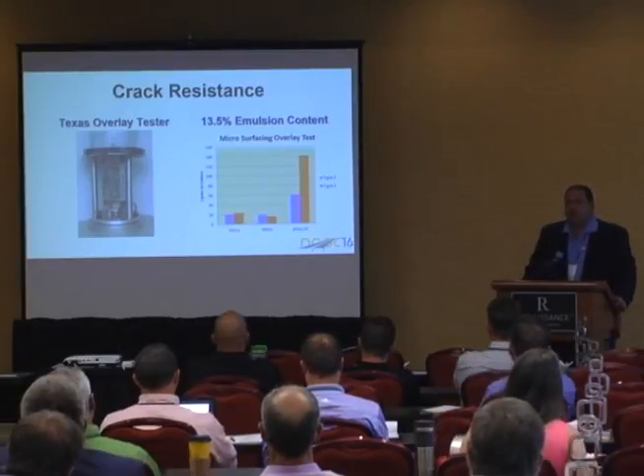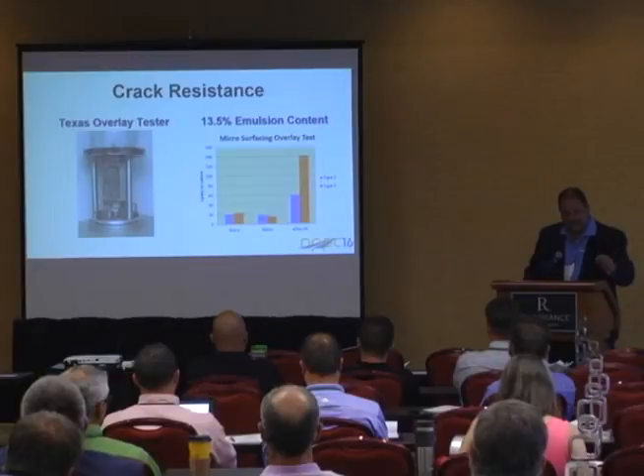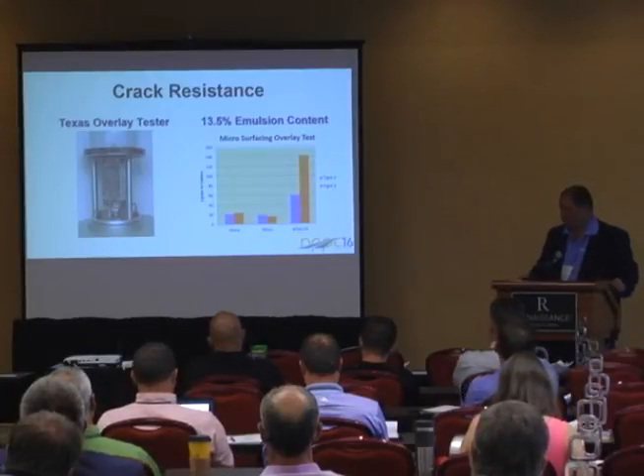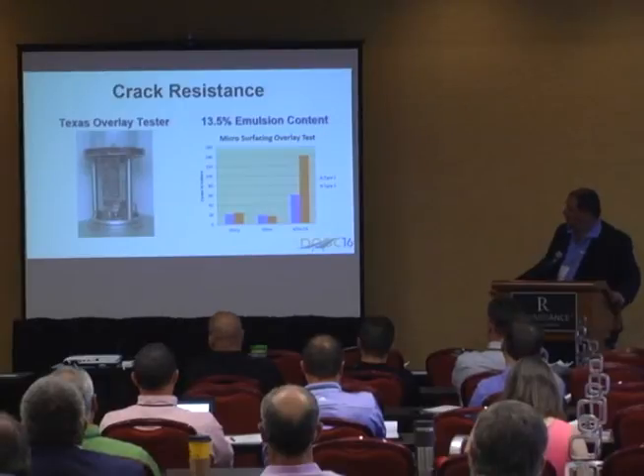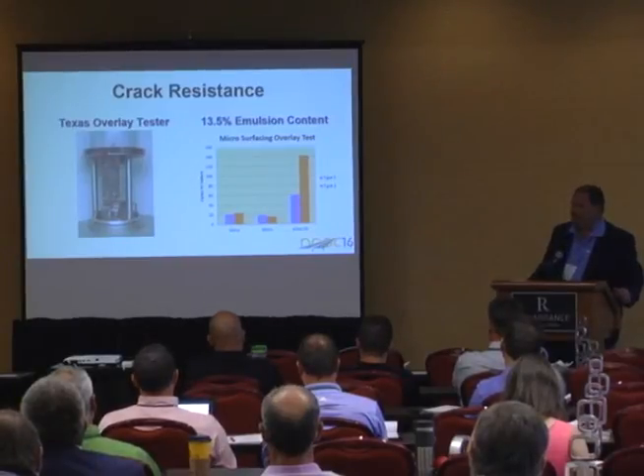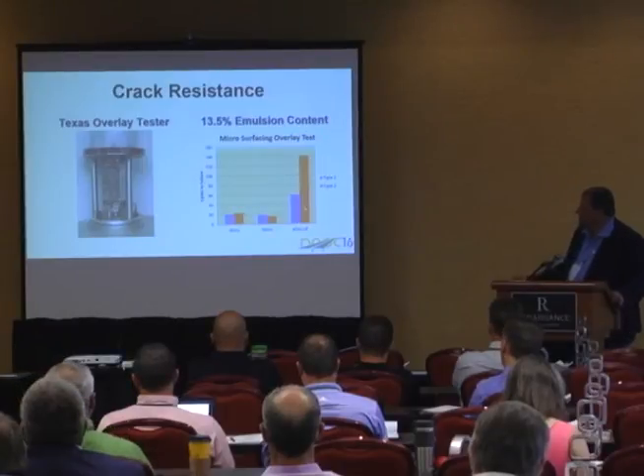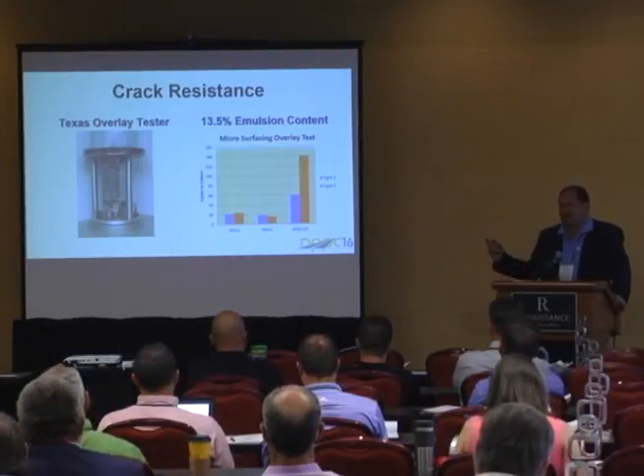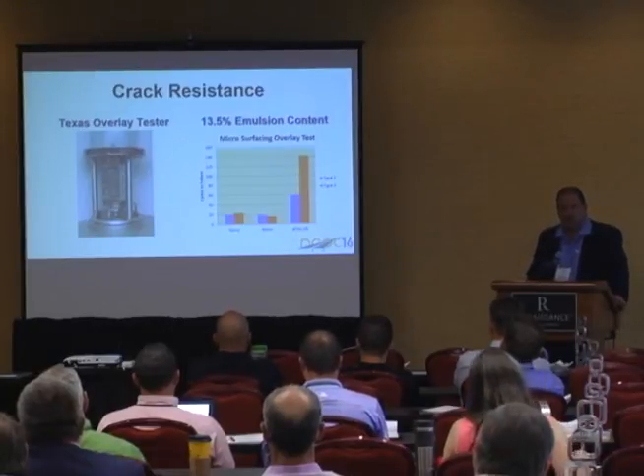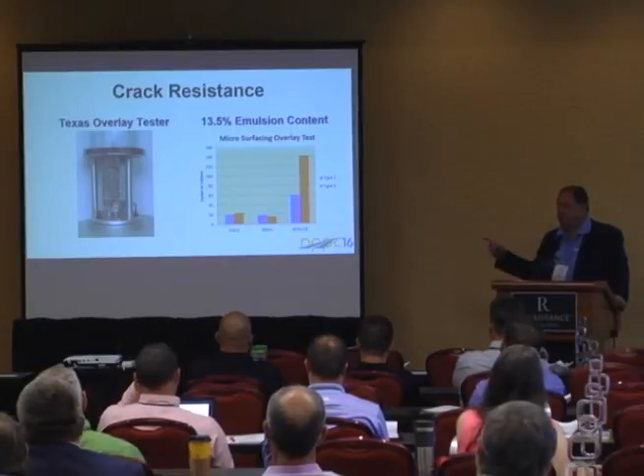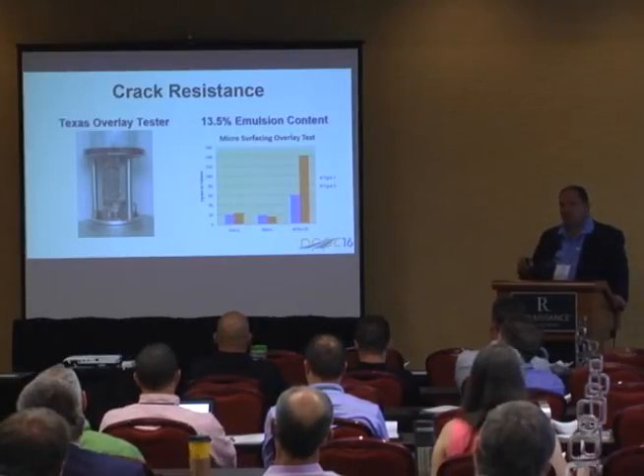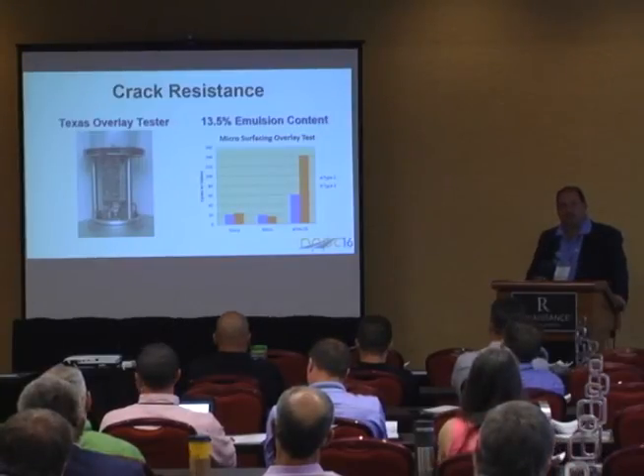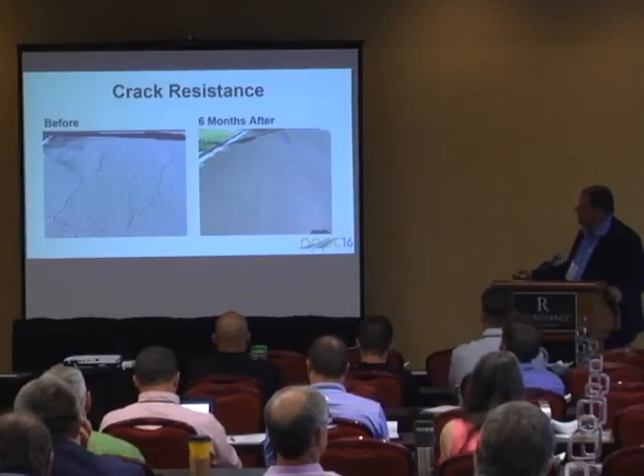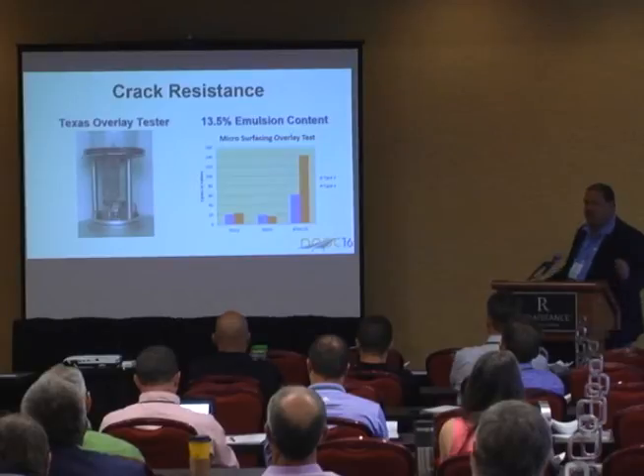But so we're looking at now, and the boys in the back room are doing a fantastic job looking at this, they're taking a modified Texas overlay tester, which applies a strain to a sample of aggregate. And this is what we're seeing with a slurry. We're getting to this many cycles here. With a micro that's modified, we're getting to these cycles here. And then with eFlex CR, which is a crack resistant, what we did here is increase the asphalt content. These are not all equal, but I think they may be all equal in the asphalt content for this testing parameter, but we went with a higher asphalt content across the board to get the most flexibility we could in these results, and we're seeing this huge gain there. But that's neat. We have a laboratory predictor.